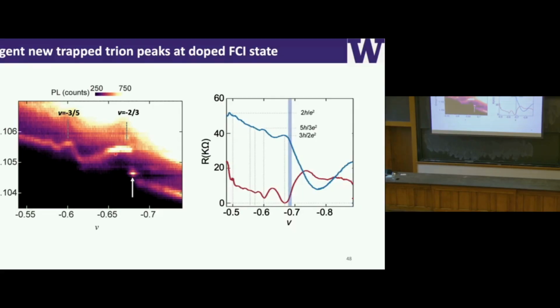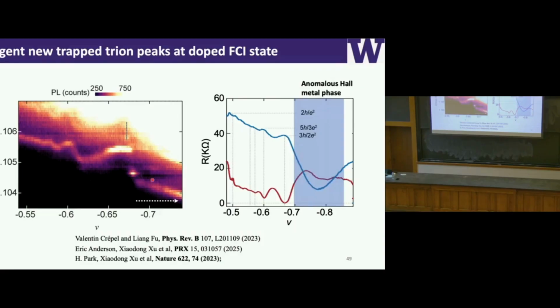Okay, so I can compare my transport, right? What's really exciting is that when I start to dope this 2/3 state just a little bit, going beyond the center of this plateau, there's an abrupt shift of this luminescence energy, and a new peak appears at the lower energies. Okay? So this new peak, I'm going to call it fractional trions.